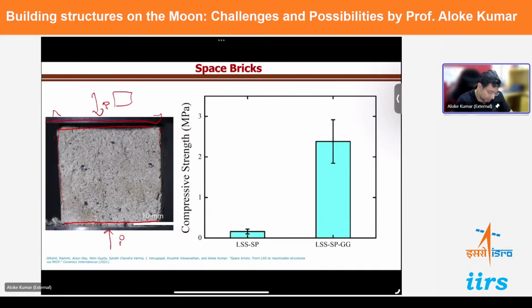And you can see now that there's a crack that has grown, right? So if you apply too much force, this brick-like thing breaks. So we studied the compressive strength for this, and when you have just the bacteria plus this SP, SP is the name of the bacteria. LSS is, by the way, the lunar soil simulant. When you just have the lunar soil simulant and the bacteria, the compressive strength is very low. It's of the order of some kilopascals. Kilopascals, by the way, just to give you an idea, it's weak enough that I can break with my own hand. Okay, it's like hardened bread that you can break.